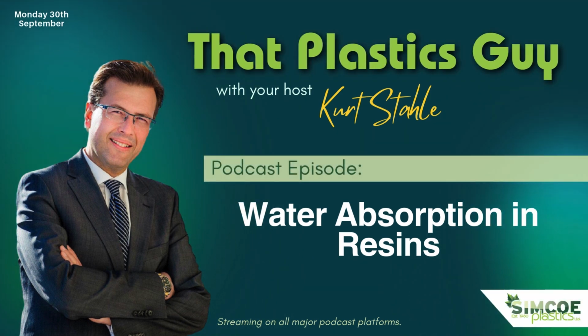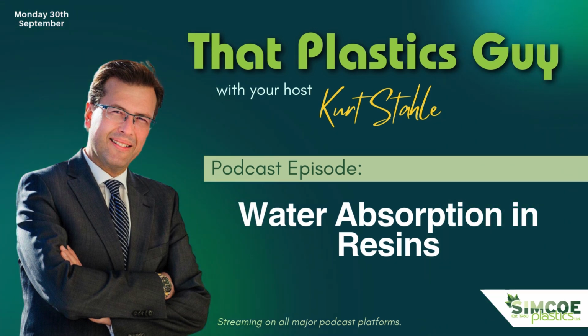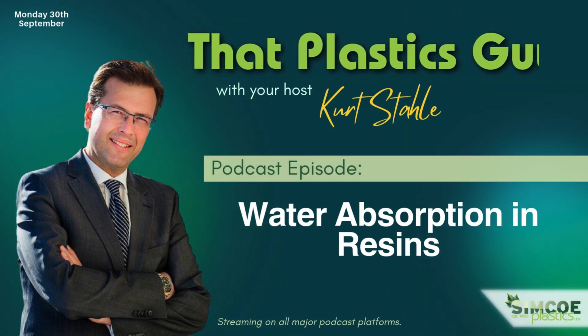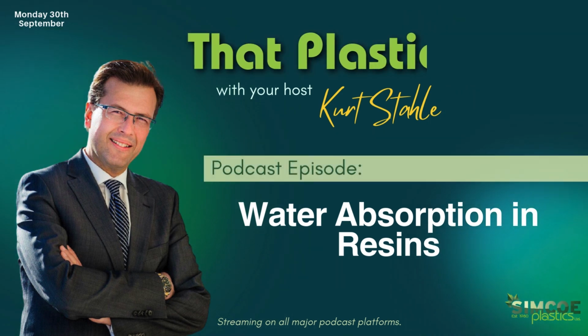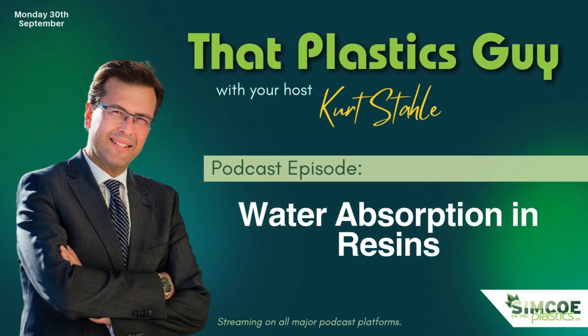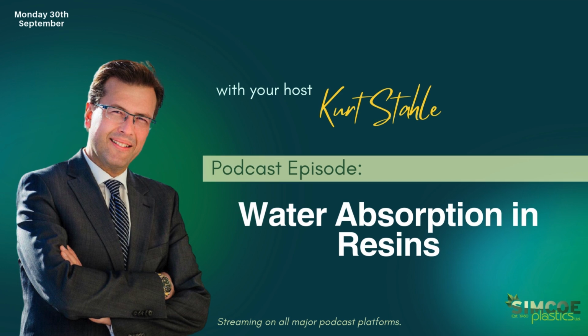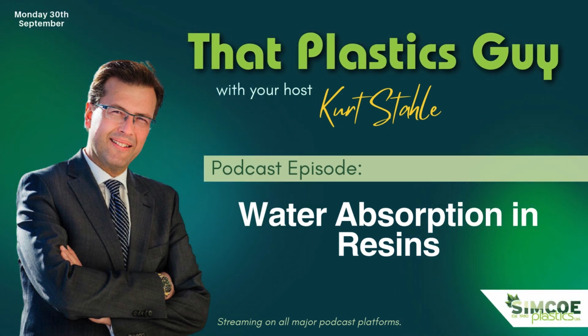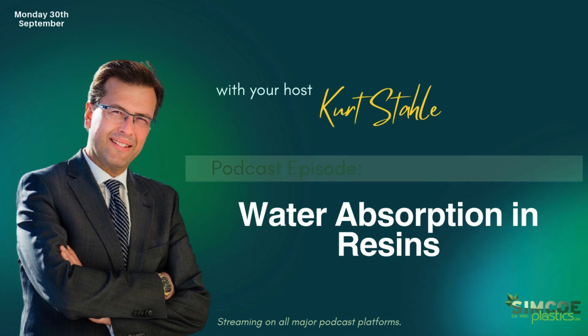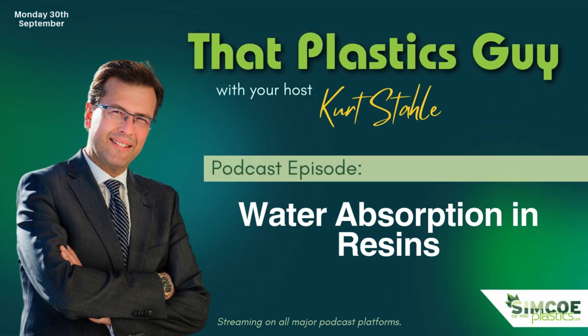So how do we test for water absorption? We're going to do just a quick rundown, then we'll get into test methodology a little bit later on in the show. Water absorption, 24-hour period at 23 Celsius: immersion of the plastic specimen in distilled water for 24 hours at 23 Celsius. That's basically room temperature, unless you're like me and I like to keep my house at 21 or even 20, even during the winter. But enough about me. Water absorption, 24 hours at 100 Celsius, so boiling: immersion of a plastic specimen in distilled boiling water for 24 hours.